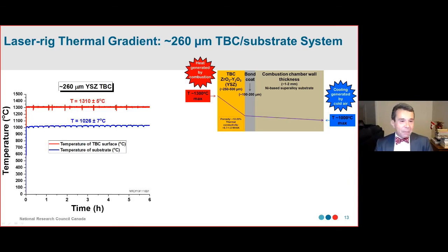And this is the graph. Okay, so during 6 hours continuous non-stop, we were able to keep the temperature of the YSZ at around 1,300 degrees Celsius, this limit here. And we were able to keep the temperature of the substrate around 1,000 degrees Celsius with this limit in here. So it's okay. We can see the delta T that we create in the laboratory is 280 degrees Celsius. So this is the TBC really working. Because at this temperature, if we didn't have the TBC, this metal would be just a goo. So this is really the TBC working.